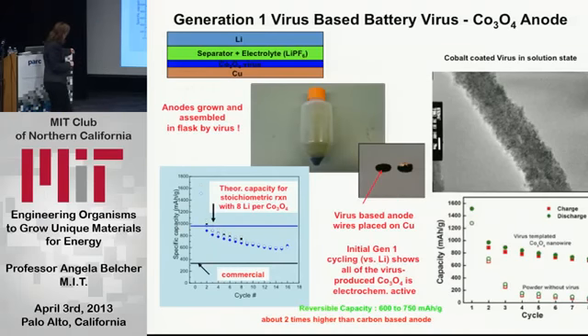But so what they were doing was testing the specific capacity of this material, and they're able to get theoretical capacity of it. But as you cycle it, it starts to decrease, it starts to fade. So we're pretty excited, become less excited and less excited. But we had a reversible capacity about 600 to 750 milliamp hours per gram, which is about 2 times higher than carbon. And we were pretty excited that it worked at all.